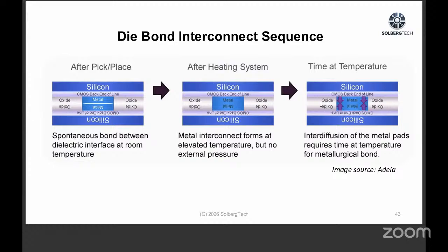Actually, there's a heating process, but it's a low temperature heating where the metal actually, I know it sounds weird, but the copper grows together in this process. It stimulates the metal surfaces. Now, by the way, these surfaces have to be just cleaned. They clean it with a very controlled process, and then they bring it together, and the interdiffusion of the two metal pads requires time and temperature, but at low temperature compared to the other processes. So anyway, it's somewhat hard to believe until you actually see the results, and it's very strong.